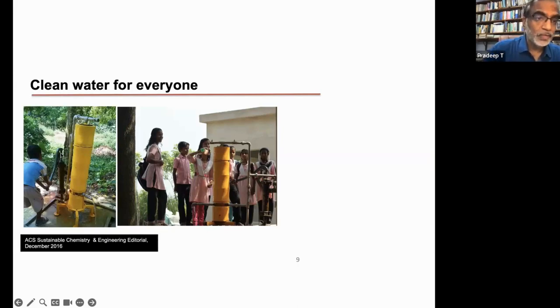The red stain is there because you have iron in water. If iron is present in water and that deposits in the form of iron oxide, there is a possibility that there is arsenic also in that particular region. So if you test it in this particular pump, it turned out that the concentration is 6 times higher than the national limit. Well, this is one pump. There are many, many pumps. It can be as high as something like 10 times or 20 times or 25 times, most commonly about 10 to 20 times in India.